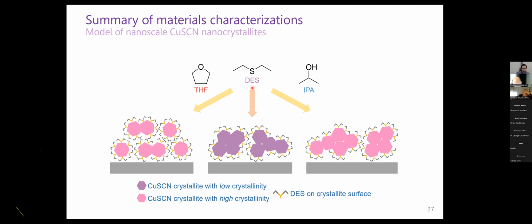The typical route of processing copper thiocyanate using DES gives a film made of crystallites with low crystallinity and some aggregations. And the diethylsulfides are likely to be on the outside surfaces of these tiny little crystallites. When we treat with THF, that leads to higher crystallinity of the grains inside and less aggregation. Less aggregation means that there are now more surfaces for the diethylsulfide to coordinate on the outside of the tiny little nanoscale grains.